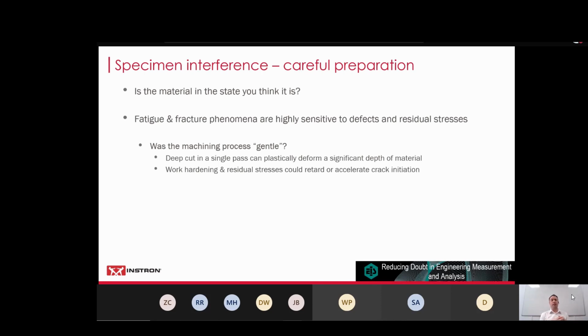Was the machining process gentle? Now, if you do a deep cut, then you start putting a lot of shear into the surface layer of material. If you are not careful, it can go much deeper than your finishing. The early cuts could actually affect a deeper layer of material than even your finishing cuts and polishing could take away. And this stuff will change your crack initiation every day of the week, and therefore it affects your test results.